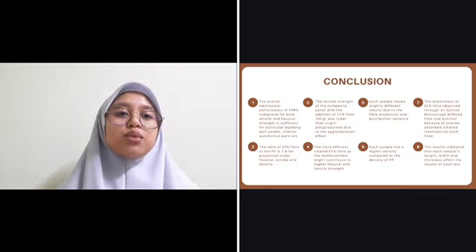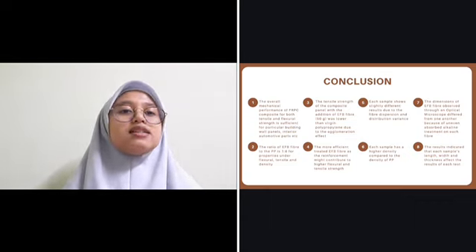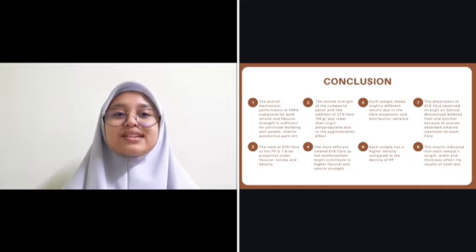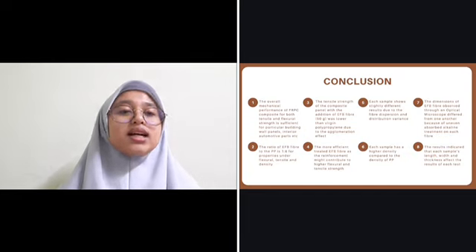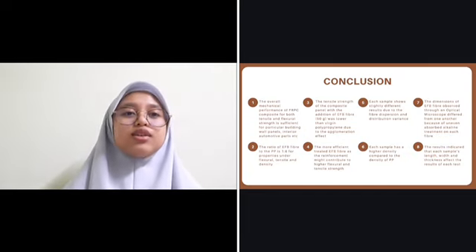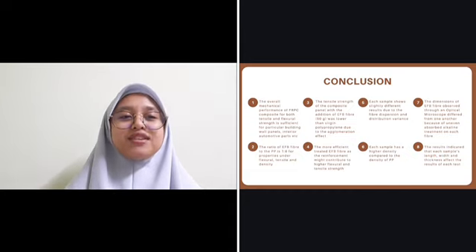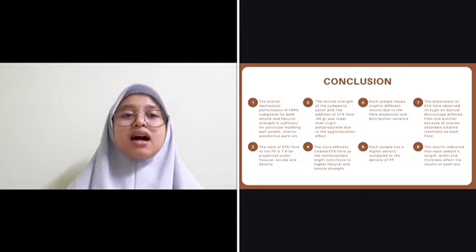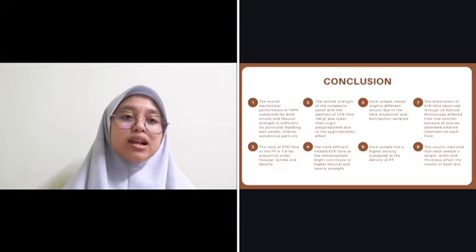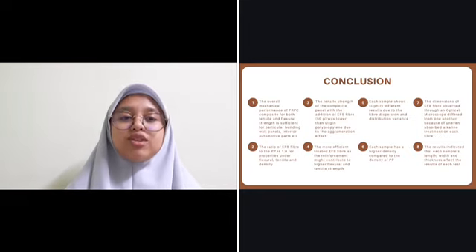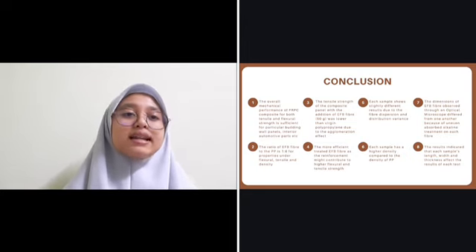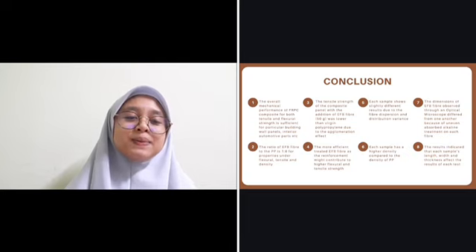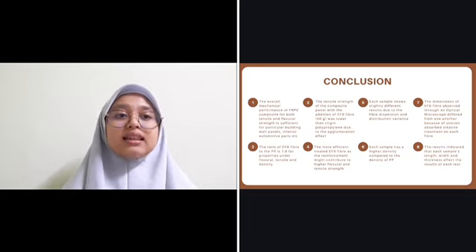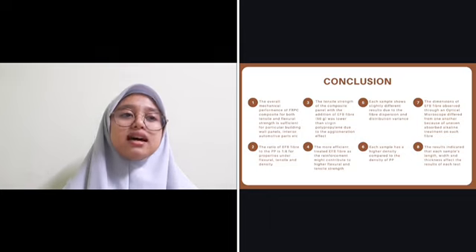The fourth one, the more efficient treated EFB fiber as the reinforcement might contribute to higher flexural and tensile strength. The fifth one, each sample shows slightly different results due to the fiber dispersion and distribution variance. The sixth one, each sample has higher density compared to the density of polypropylene. The seventh, the dimension of EFB fiber observed through an optical microscope differed from one another because of uneven absorbed alkaline treatment on each fiber. The last one, the result indicated that each sample's length, width, and thickness affect the result of each test.